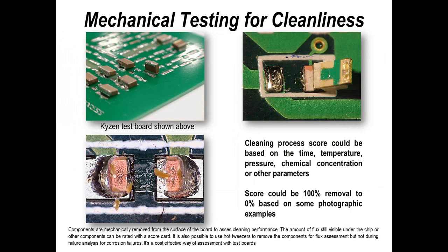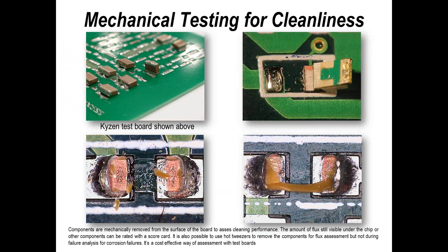Another simple way of looking at cleaning compatibility is a demonstration used by the team at Kyzen at the last two practical workshops at Productronica and Apex. They take boards, solder them, and by mechanically removing residues after different cleaning process steps, assess the level of cleanliness. In their laboratory, they look at the volume of material and put a score on it after cleaning. It's much better to break the component off rather than use a soldering technique to remove it, as you then see the total residue left behind — a destructive but fairly simple evaluation technique.